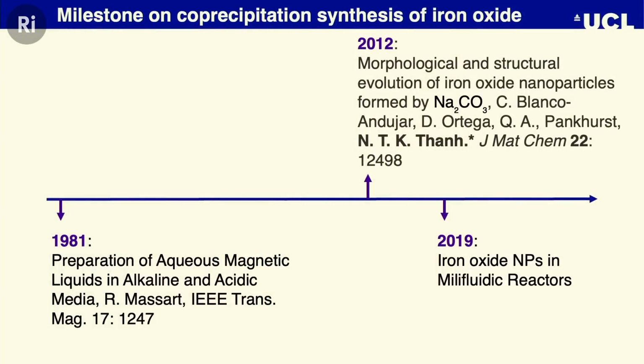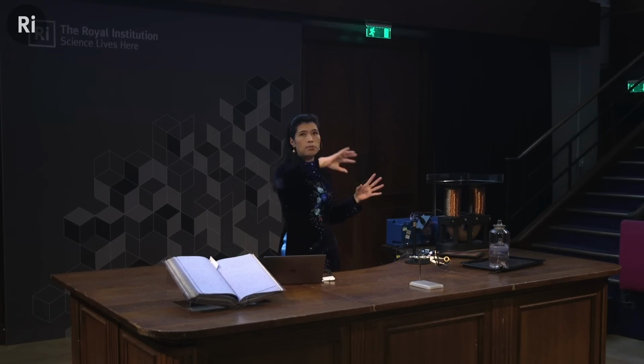Then this is a work we published in 2012, but actually this work started at the Royal Society Summer Science Exhibition, in collaboration with the RI, Professor Quentin Pankhurst, and our group had a big exhibition, and we wanted to show the public how we make this iron oxide. Sodium hydroxide is very caustic, so we wanted something milder, so we used baking soda. So we could make the nanoparticle using baking soda. Then Christina was a PhD student between myself and Professor Quentin Pankhurst, and we systematically studied it. And from that work, what we showed is that with the mild base, you form a lot of intermediates. And remember that iron oxide has more than 10 phases, and not all of them are magnetic.